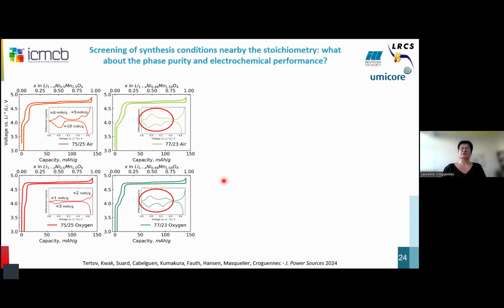If we look more carefully at the electrochemical curves, here you have the air materials, the oxygen materials, here the stoichiometric, and here the excess of manganese. You can see that we have slight modifications of the electrochemical signature. For this stoichiometric composition under oxygen, we are really able to have an almost pure stoichiometric material with an ordered signature in this derivative, despite a small amount of manganese 3+, as you can see from this signature and this jump. For these other compositions, we have much more complicated evolutions, with two peaks in the derivative curve obtained for manganese-rich materials.